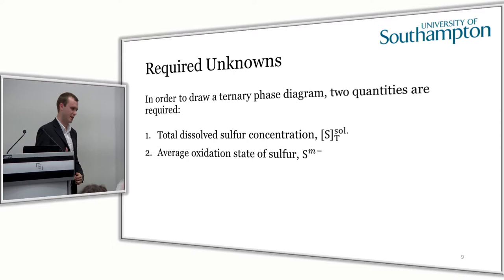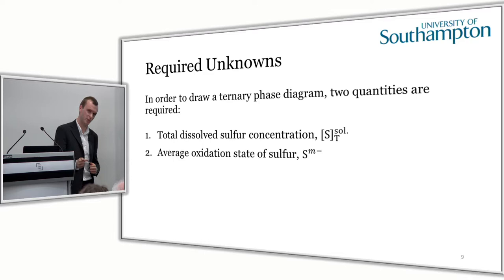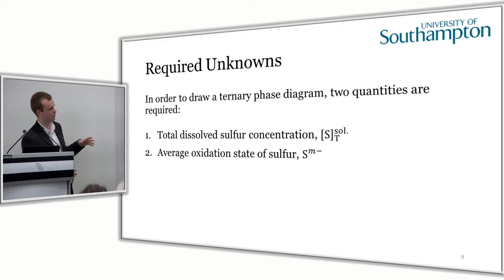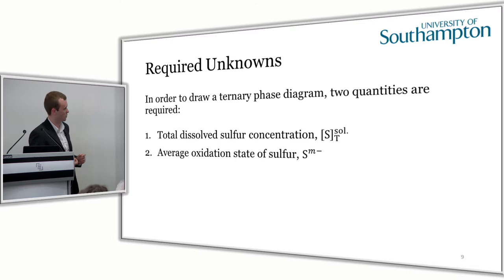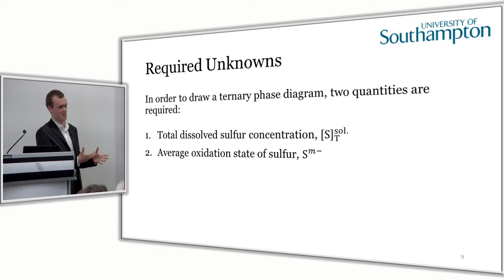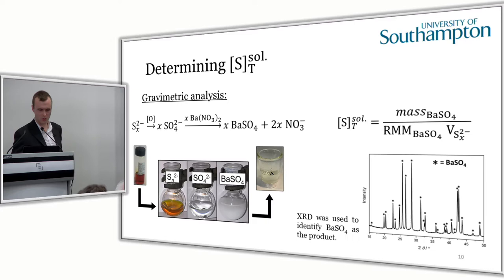There were two unknowns needed in order to build our phase diagram. The first was the total dissolved sulfur concentration — the concentration of sulfur associated with dissolved sulfur, any polysulfide species, or lithium sulfide. In terms of the phase diagram, this represents how far up or down the y-axis we are. The second was the average oxidation state of sulfur, which can be thought of as our x-axis — how close to fully charged or fully discharged we are.